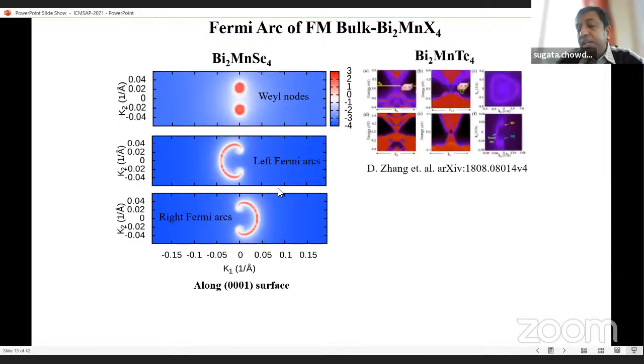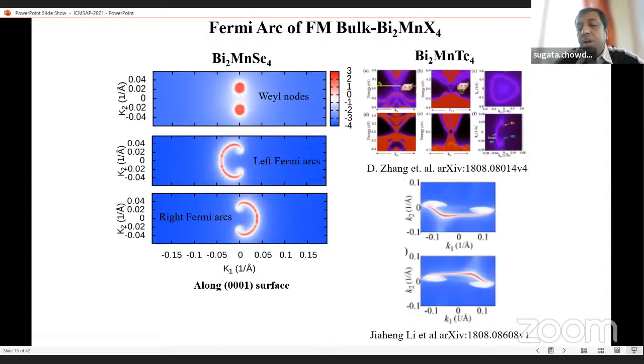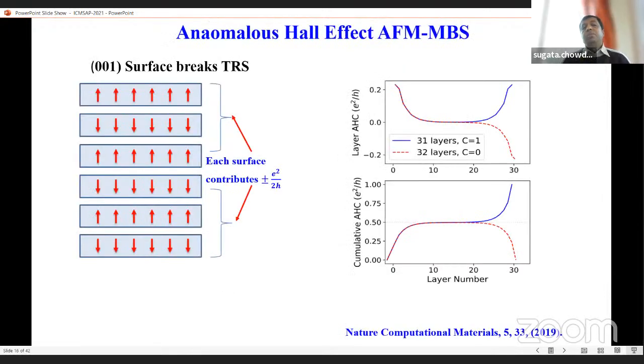When we were working on the MBS system, a different group was actually working on the MBT system, and they found a similar kind of property for MBT. And from there, we found that this material, or family of materials, is a really good candidate for observation of the quantum anomalous Hall effect. So we found out how it works. What is its transport property?